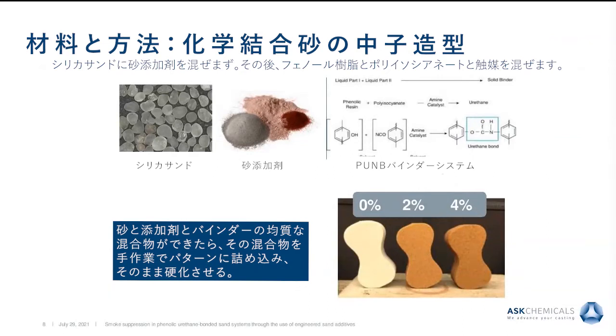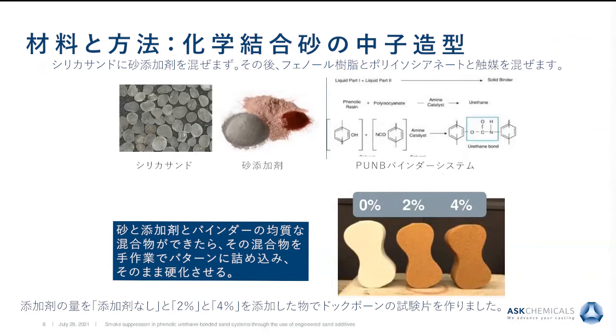Just to show below some examples of the small specimens we use in the lab, so people are familiar with the dog bones. We can make dog bones at different conditions. Always, of course, we use a control specimen, which is the one with no additive, and then we can change the level of the additive to 2, 4, 6%. And later on, I will show why we use a particular range for this sand additive.